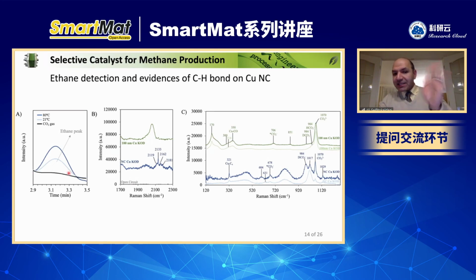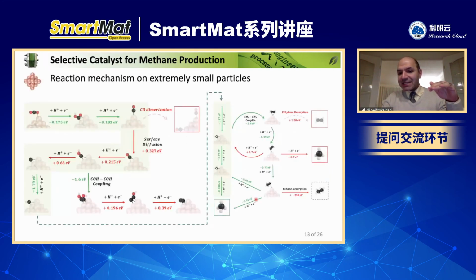But we did the same experiment with large particles. There was no ethane, neither at room temperature nor at higher temperature. So that means on larger particles such as 100 nanometer or 200 nanometer, there was no such mechanism that the ethane is adsorbed on the surface. So we didn't have that procedure. In fact, once the ethylene is produced, it just leaves the surface on large particles. So there's no chance for having the ethane. I hope I answered the question.